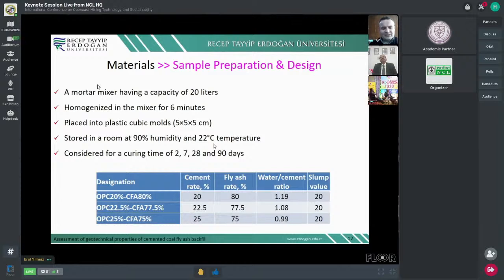So in this study, we got 4 different curing times. The reason for those waiting times belongs to the schedule time at which coal will create some subsidence, especially for example 3 months later. There's no importance to get it because you will complete all the extraction procedure within 3 months. Here also some values, water to cement ratio. We also keep the constant slump value at 20 centimeters.